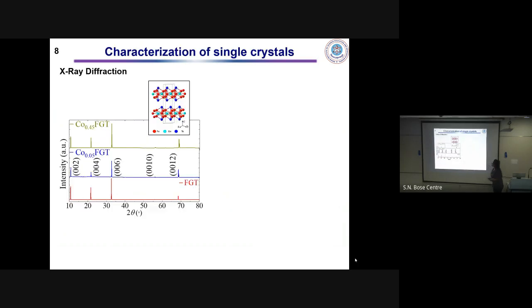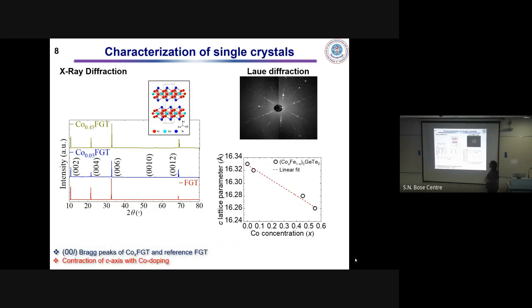Okay, moving on to the characterization of the single crystals. Here you can see the X-ray diffraction pattern for Fe3GeTe2, hereby I'm calling it FGT, and two of the doped compounds. For all the compounds, the XRD patterns that we have observed, these peaks could be identified as 00L Bragg peaks for both FGT and CoxFGT, which confirms that the crystal basically grows along the c-axis and the exposed plane is the ab plane. Okay? And we have also performed Laue diffraction, which confirms the high quality of the single crystals.